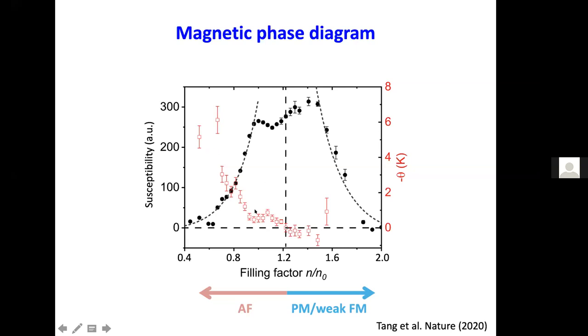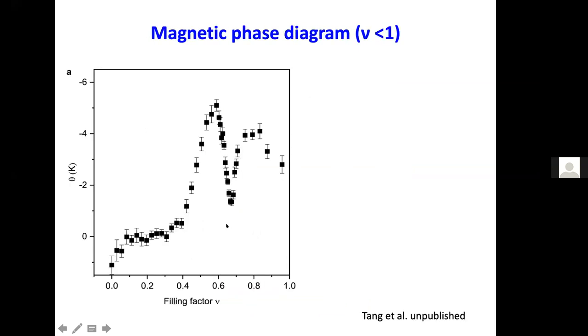After that we look at what's going on for the fractional filling more carefully - this is a more careful measurement. You can see that the antiferromagnetic interaction is very weak for small filling, which is understandable because the particles are far away from each other. Then it also goes down close to 1 because at that point the Mott state settles in, and in between there's some kind of peak, but surprisingly we saw a very large dip right at 2/3.